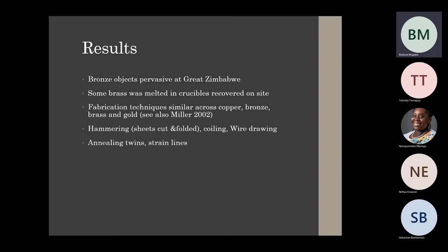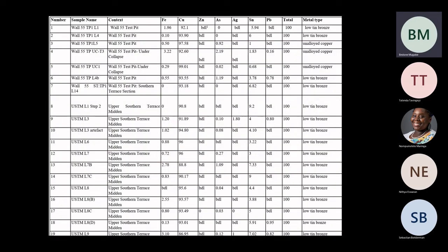So wire drawing is also evident at Great Zimbabwe, and this was evident because of the annealing twins and the strain lines that were exhibited within the microscopic pictures, the photomicrographs, and the BSE backscattered electron images that are shown below. Next slide, please.